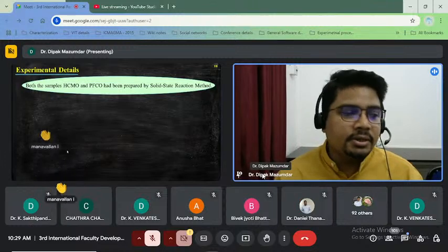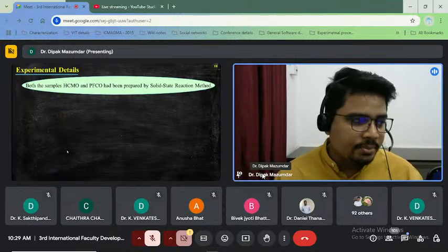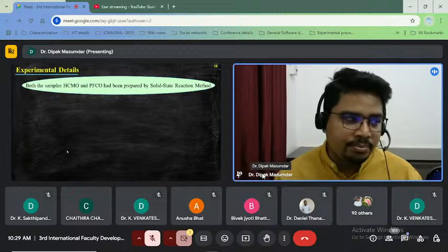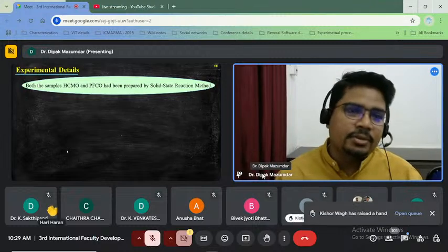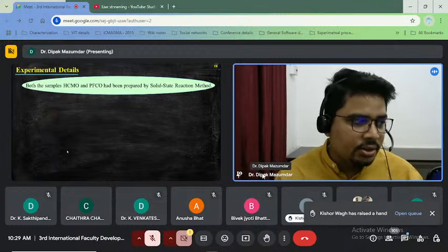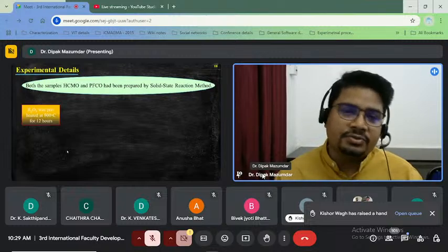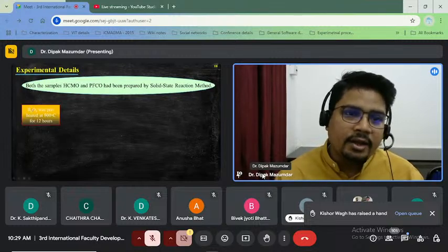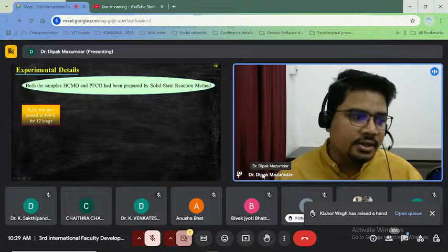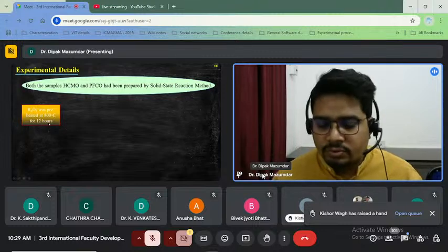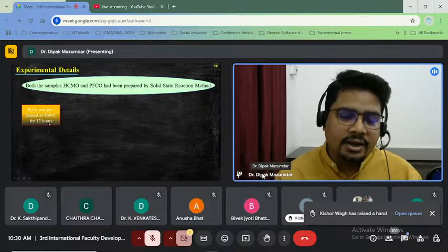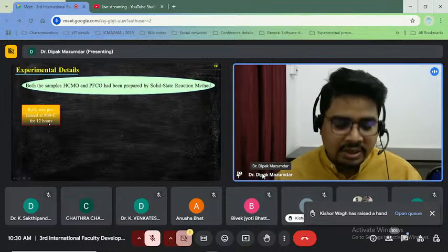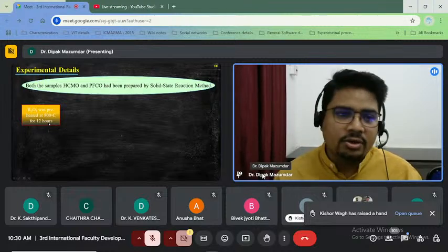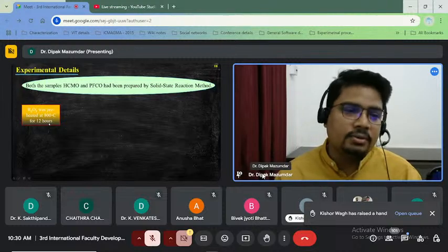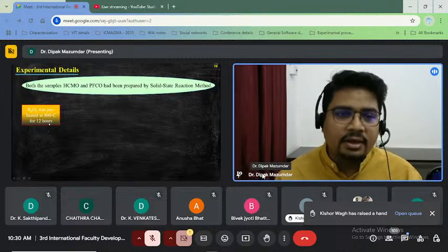Now come to the experimental details. Both the samples HCMO and PFCO were prepared by the well-known solid state reaction method. According to this method, the rare earth oxide was preheated at 800 degrees centigrade for 12 hours. All of you know we should preheat the rare earth oxide overnight because it may have some moisture or carbon molecules, so we should preheat it before weighing the compound.